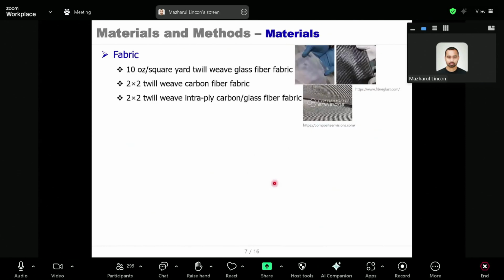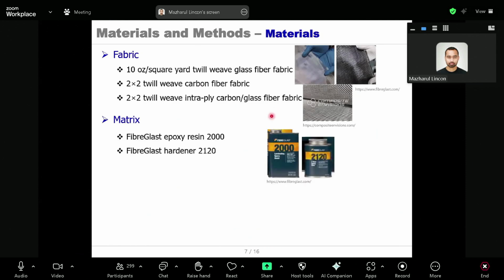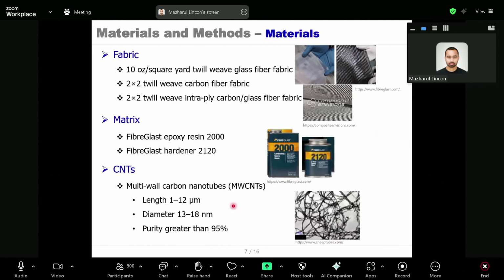The material used for this study is twill weave glass fiber fabric, carbon fiber fabric, and hybrid glass-carbon fiber fabric. The resin used is FibreGlast epoxy resin and hardener, and multi-wall carbon nanotubes are used to make the interlaminar hybrid composite conductive.